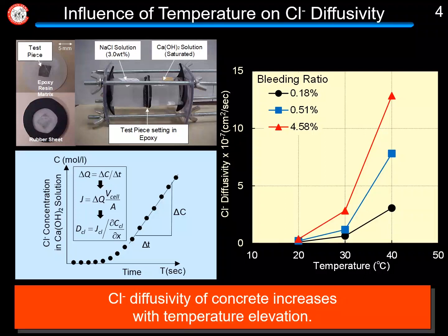First, I would like to explain the result of temperature dependency of chloride ion diffusivity. You can see the testing procedure here. In this study, a 5 by 5 by 0.5 mm test piece taken from concrete was used for investigation.